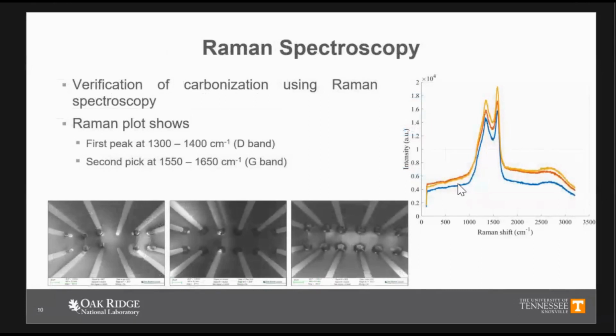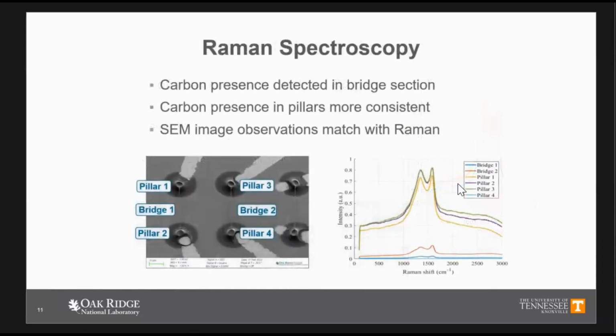Next, for the verification of the nanoelectrodes, we used Raman spectroscopy. As you can see, there are two peaks, the Raman D band and G band, which basically shows that sp2 carbon structures are present in the structures. We also did Raman for pillars and bridges together to see whether they have the same kind of profile in Raman spectroscopy. This also verifies the SEM image observation that there is carbonization.